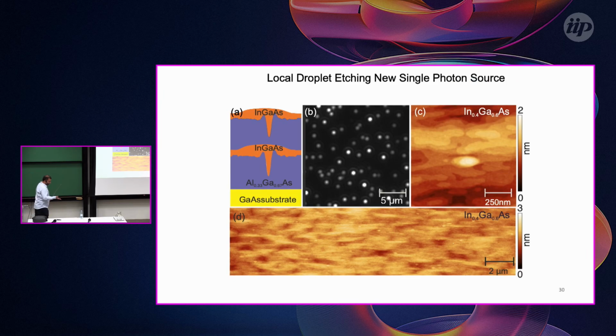Why did I do this? Because companies like Quandela and SPARROW Quantum are selling sources in this range. And I was thinking, should it be possible to extend this method to 920 nanometers and get the same optical quality as the gallium arsenide quantum dots? Basically what I did was very simple. Instead of filling these nano holes with gallium arsenide, I included indium in the structure. People before were trying to do this, but instead of gallium, they were trying to fill the nano holes with indium arsenide.